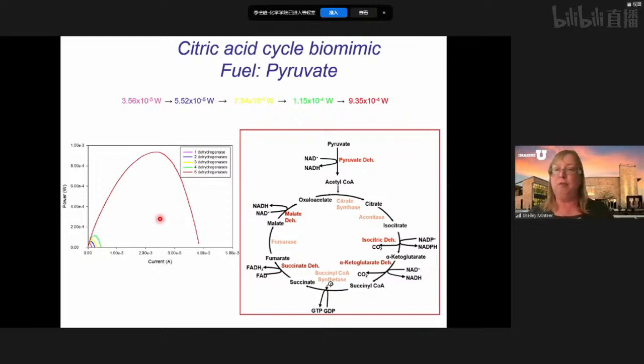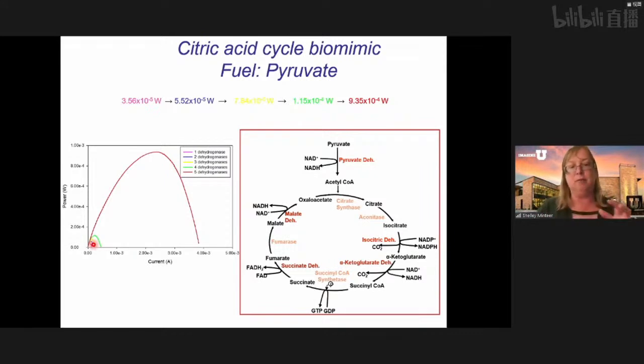And so you'd expect as we go from 2 electrons to 4 electrons, we would double our current, and since power is current times voltage, we would double our power. So we would see this doubling, tripling, quadrupling of our power curves. And when you look at the power curves, you can see down here in pink when we're just doing that 2 electron oxidation of pyruvate. When we go from pink to blue, we see an increase in current. Then from blue to yellow, another increase, but we're not quite doubling and tripling until we add this final enzyme, malate dehydrogenase, to the system. And we see this huge 26-fold increase in current density and power density.